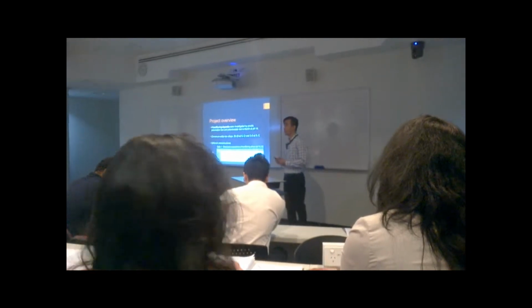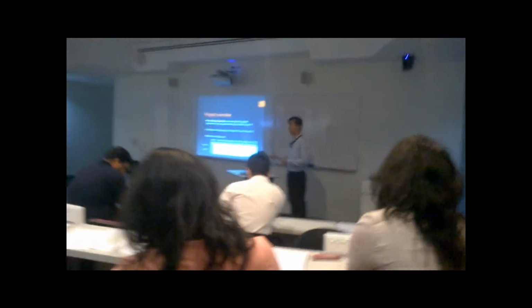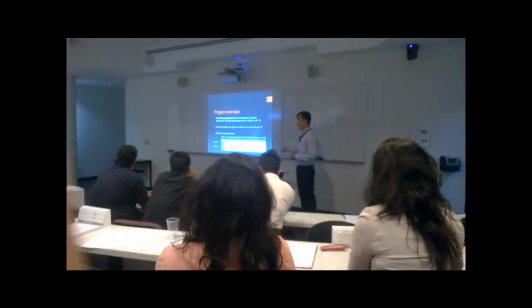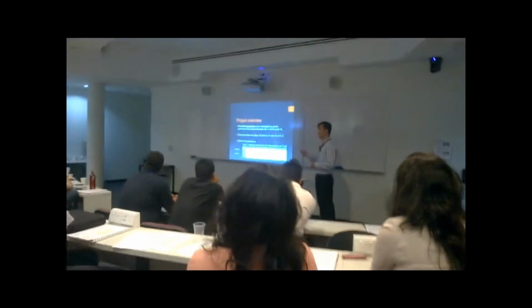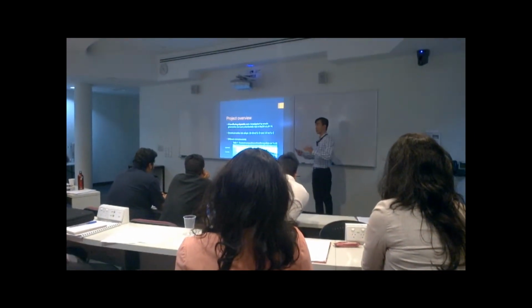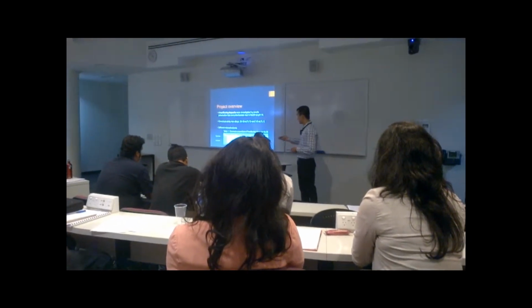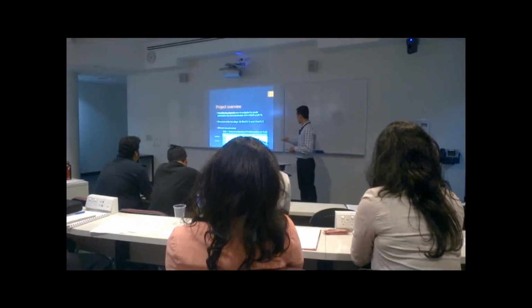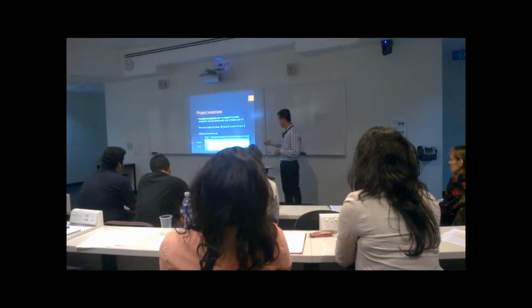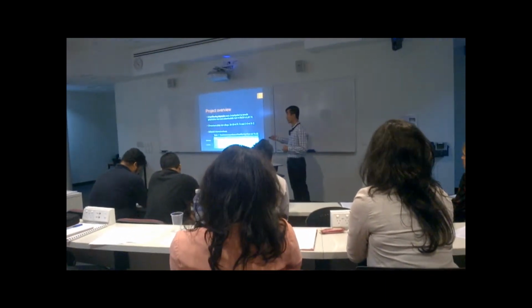So with very high content of chromium and carbon, it benefits the formation of a compound named carbide, a compound formed between the metal and carbon with very high hardness, and that's why these materials have a very high hardness. So typically, these materials have microstructures of carbide forming on an iron matrix, and the addition of other alloy elements changes the iron matrix to different microstructures. Basically, we got the alloy D with a martensite matrix, and alloy 1E, 9E, and S have an austenite matrix.